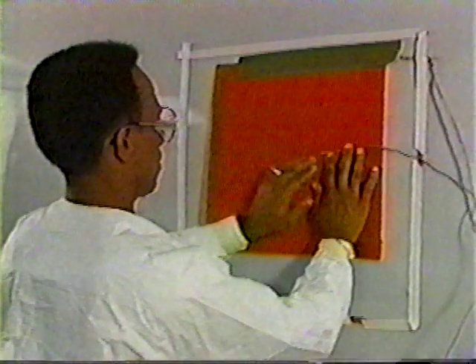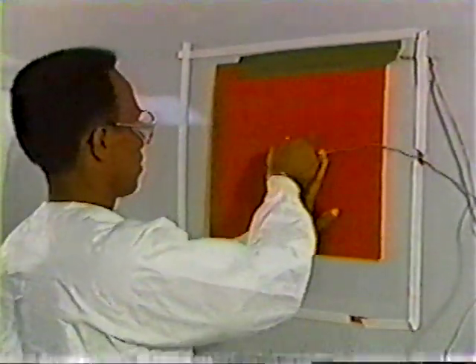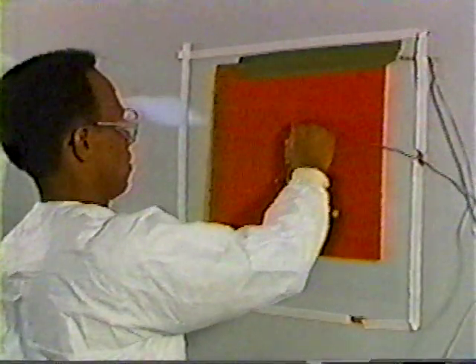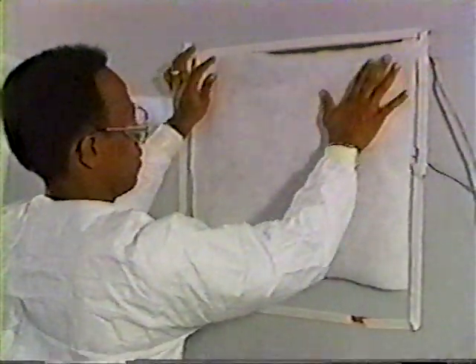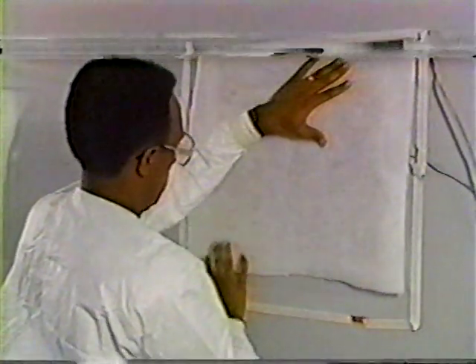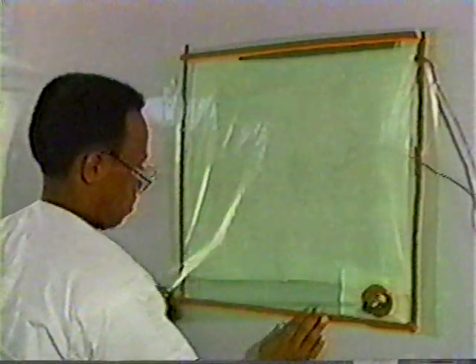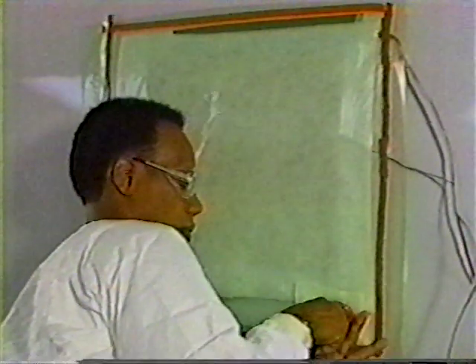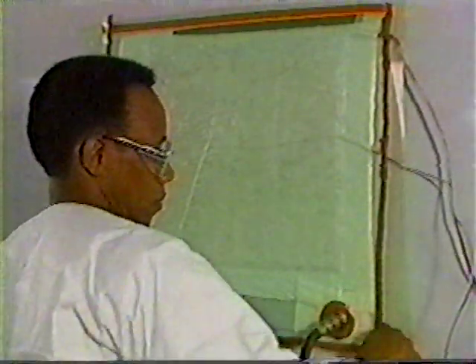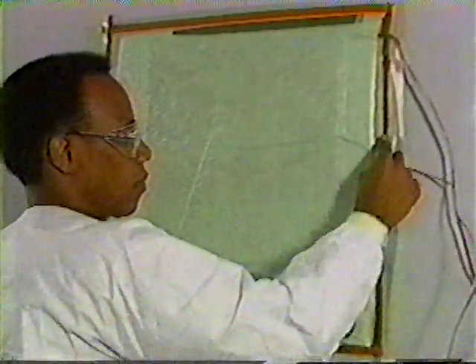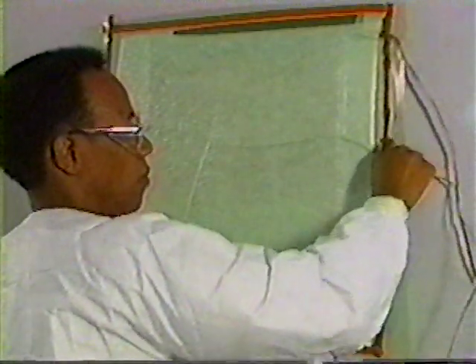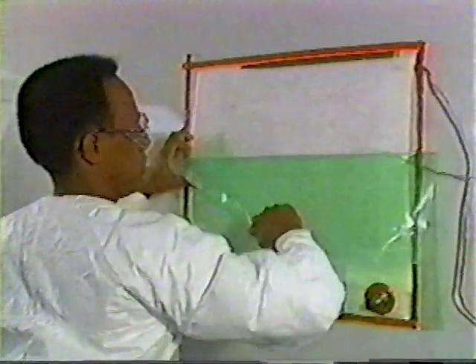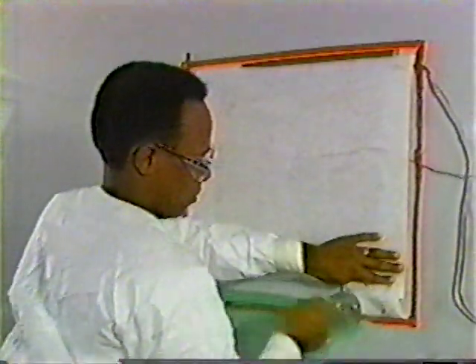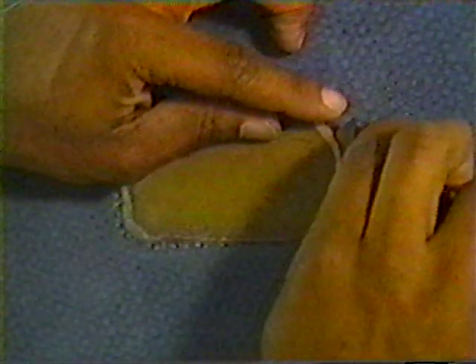Next, place a temperature probe at the center of the heating blanket and secure it into place with tape. Then, position one sheet of RC 3000 breather material over the heating blanket, followed by the nylon bagging film and vacuum probe. Evacuate the air to at least 20 inches of mercury. Then, cure the repair at the times and temperatures specified in the SRM. When the cure has been completed, remove the bagging materials from the repair area. And finally, remove the peel ply material from the fiberglass cap.